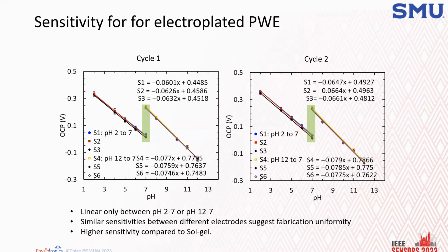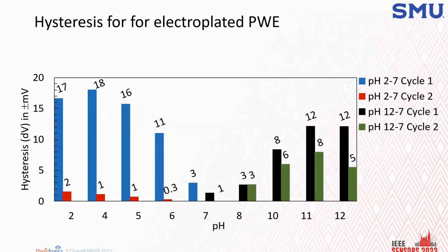This means that if we use an electroplated electrode for pH sensing, we do need to calibrate towards 7 to make sure that 7 will give you the same potential. And for this electroplated one, we did find the slope is higher than the Sol-gel one, which means the electroplated sensor has a better sensitivity. And this is the result for hysteresis. Again, blue and black are the first cycle, and red and green are the second cycle. Again, it shows that at the second cycle, the hysteresis almost disappeared. That means fixing the drift problem did fix the hysteresis issue.